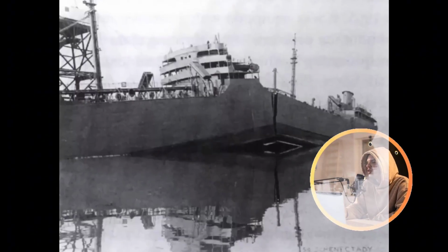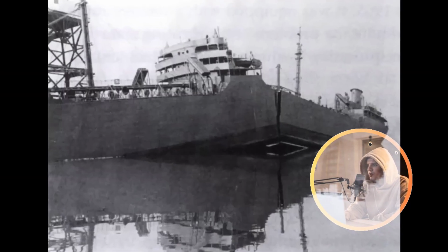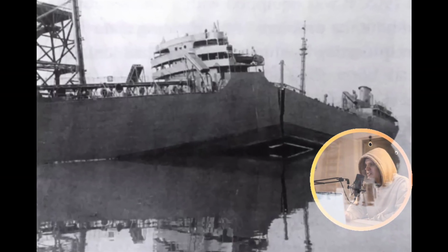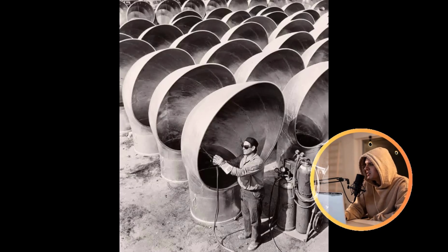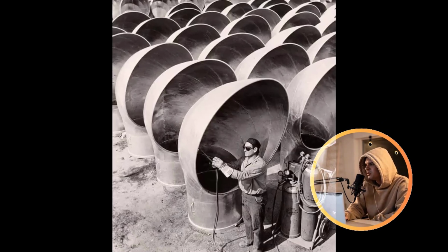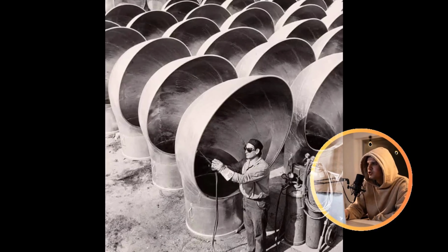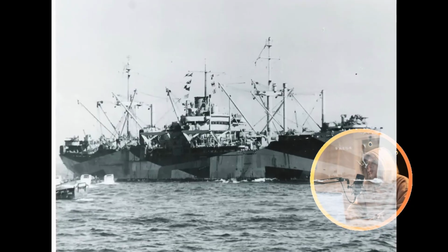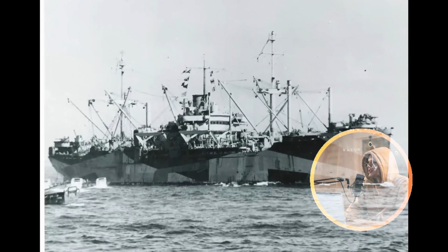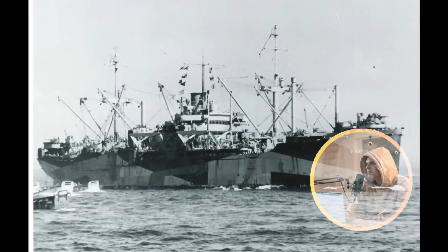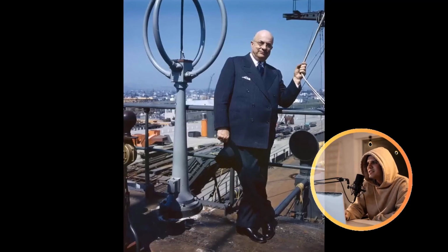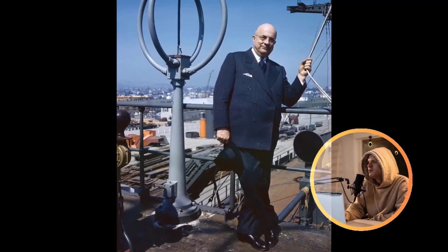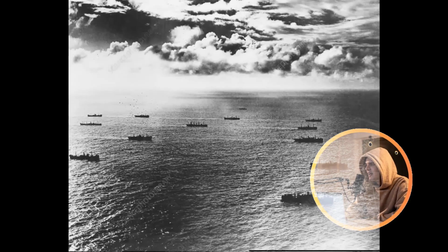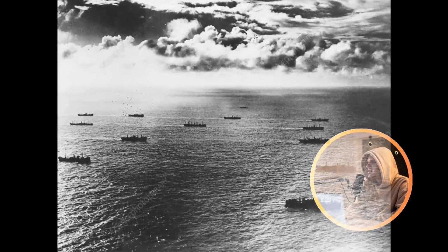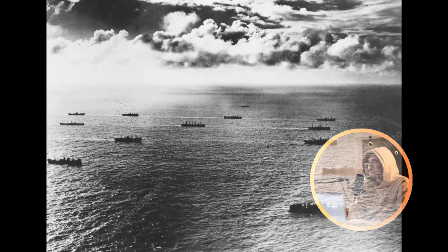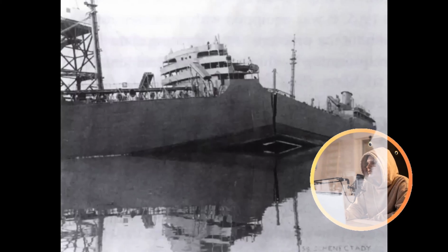This fissure then followed an unobstructed trajectory through the continuously welded deck plates, encountering no riveted seams to impede its progress, nor any engineered stress relief breaks to halt its advance. The fracture consumed the vessel in a matter of seconds, unleashing decades of accumulated energy in a single, calamitous event that tore the ship apart. Conversely, traditional ships, meticulously assembled with rivets, did not typically succumb to this particular mode of failure, and understanding this distinction shed considerable light on why the then nascent practice of welding appeared to be fraught with peril.